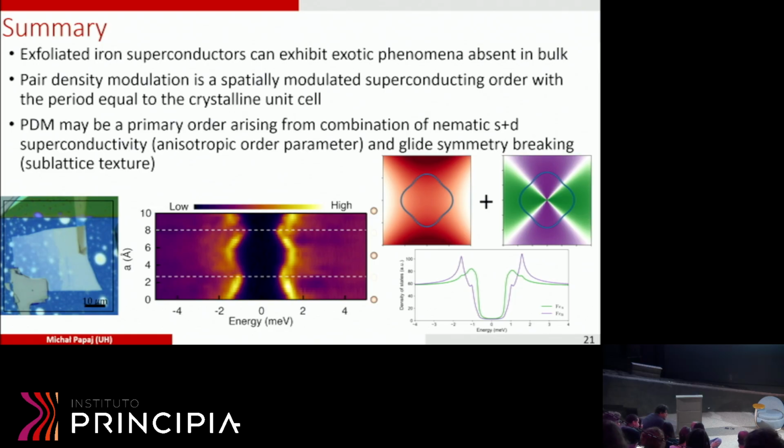Just a clarifying question. Earlier, when you showed the experiment, there was a Q2 vector that was missing. Maybe I missed the explanation. Is the explanation related to the sublattice weight? Why is the Q2 missing? Q2 means that we either don't have a gamma pocket or we don't have an M pocket. So you're attributing it to the lack of the actual pockets. Right. And this was seen in some iron superconductors that don't have either of those pockets, the monolayers.